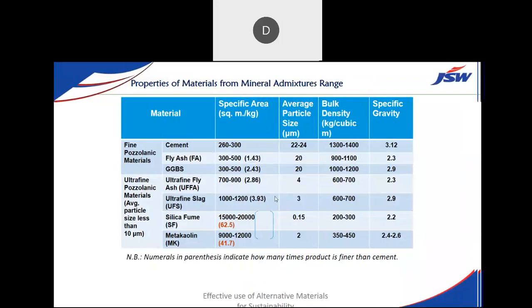These are the specific area, the particle size, the bulk density, the specific gravity, everything is tabulated here. Fly ash and GGBS are almost similar in nature in terms of fineness and specific gravity. We are comparing with cement only. The fineness is there. The average particle size is also the same. Fly ash specific gravity is 2.3, whereas GGBS is 2.9. 2.9 is similar to pure OPC cement, which is 3.12 or 3.15. So what I'm telling you is that between GGBS and fly ash, not much difference is there. Both are similar products. That's the reason we are able to replace a higher percentage of GGBS in the concrete matrix.